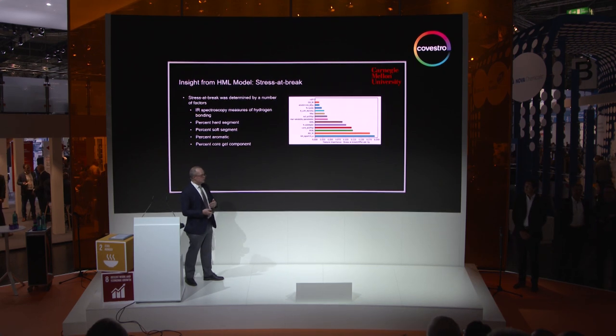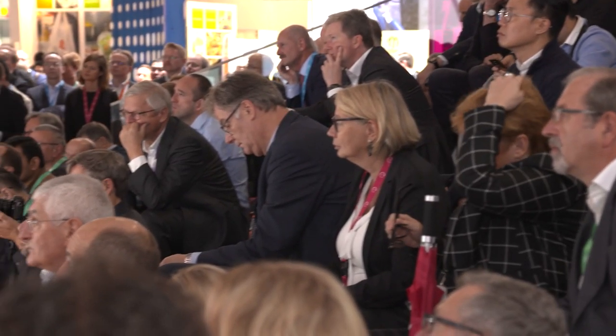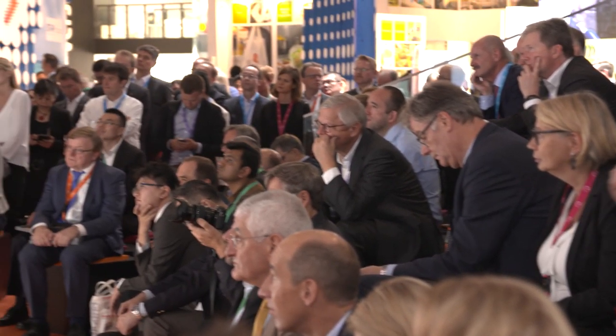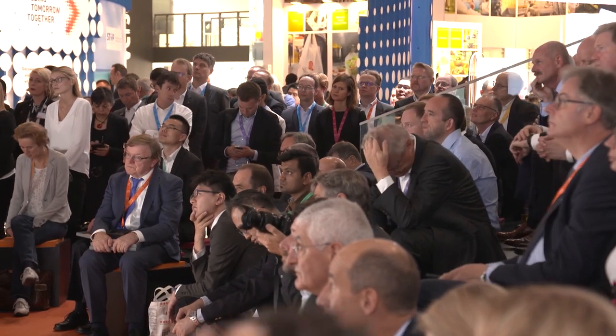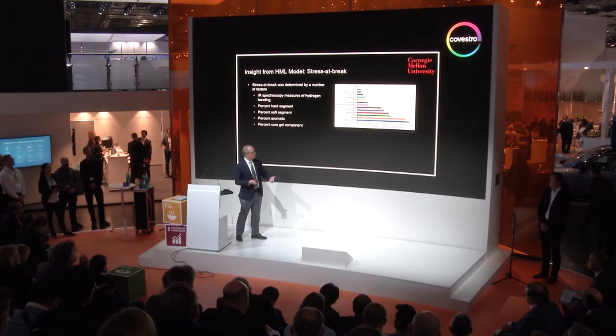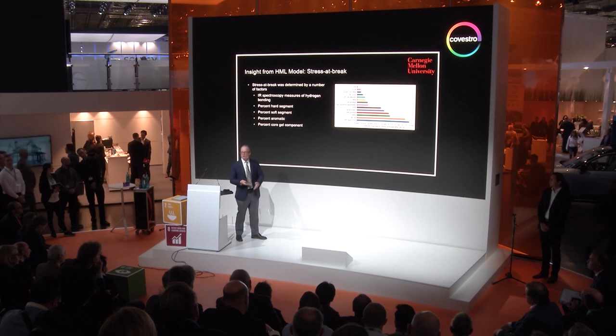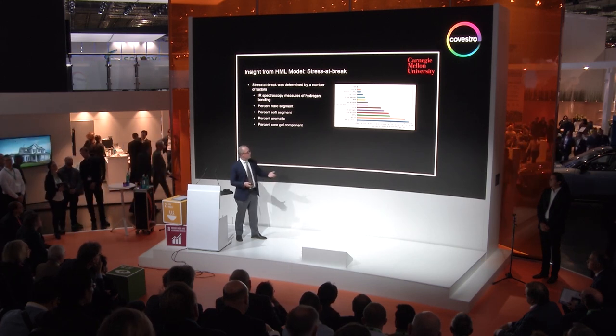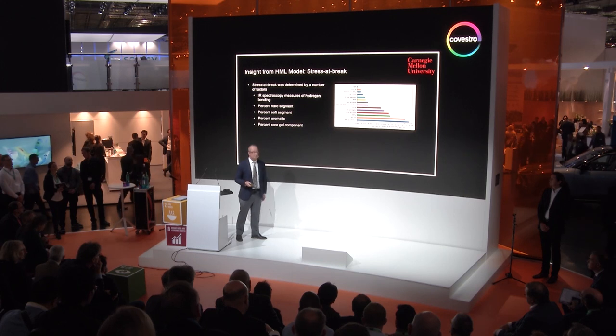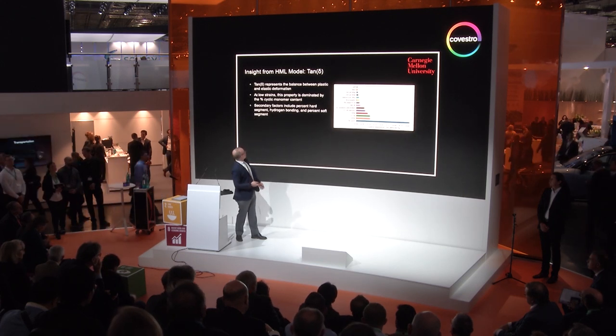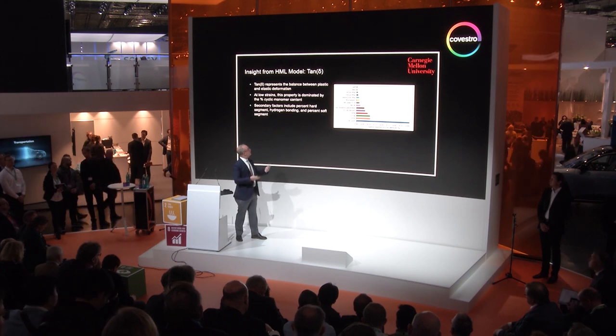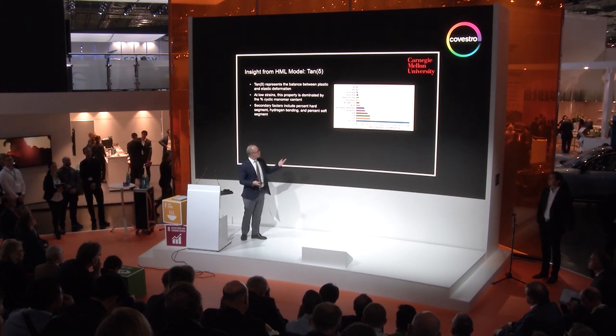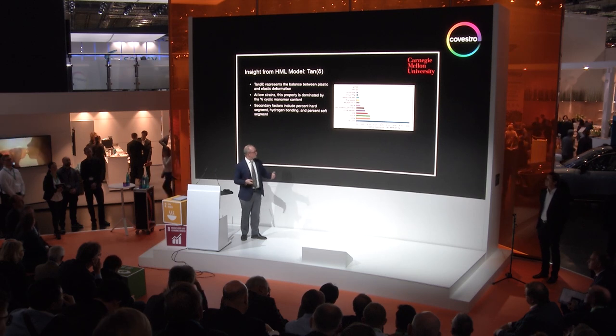The algorithm then starts to tell us how it thinks these systems are working. For example, the algorithm is making the prediction that the stress when the sample is breaking is actually dominated by the intermolecular hydrogen bonding of these materials. So it will try to explain how it works, and we can use that to further refine the model. Interpretation of this is important because what we're really trying to do is develop a design tool. And then in contrast, this ratio of the elastic and the viscous responses is heavily controlled by the chain architecture that's forming, which is shown here.